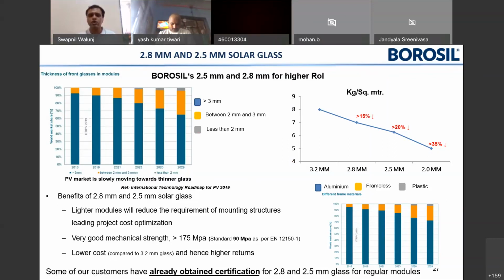They also have a very high mechanical strength, at least 175 megapascals as compared to the 90 megapascals mentioned in the specifications. And these two, 2.5 and 2.8, have a lower cost. So ultimately, you will be able to realize higher returns for your modules, because you will end up saving some cost on these two types of glass.